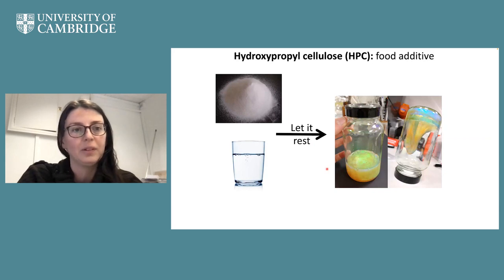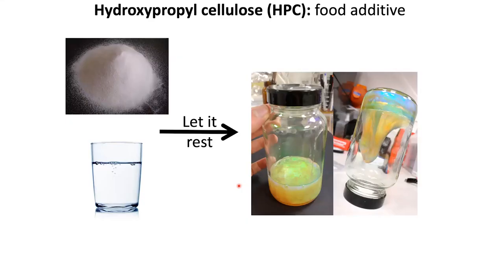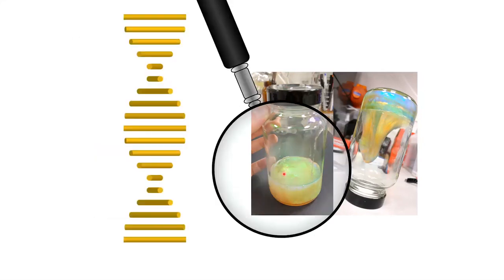But maybe what you don't know is that if you mix this hydroxypropyl cellulose simply with water, and you let it rest, you start to form this beautiful coloration. It appears just by letting the suspension rest for a couple of days, at high concentration, 60% hydroxypropyl cellulose and the rest water, in a vial. So what's happening? If you look macroscopically at this film, and you look at how the polymer chains are organized in this type of system, you notice that they are forming a helicoidal-like architecture, which you would call a liquid crystalline phase, a chiral nematic phase.